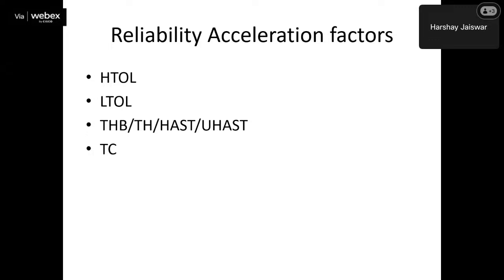Next, TC, called temperature cycling. Again, depending on the qualification plan, different types of temperature conditions are applied. But mostly used are -40 to 85 degrees, -40 to 125, -40 to 150, -55 to 150, and -65 to 160 degrees. What we generally do is place the part into the oven, and the oven is programmed for how many cycles we need to run, low to high, low to high. Generally it's for 1000 hours. After this, we have certain intermediate readouts, as I mentioned for the HTOL. Then we check whether the device is passing or failing.